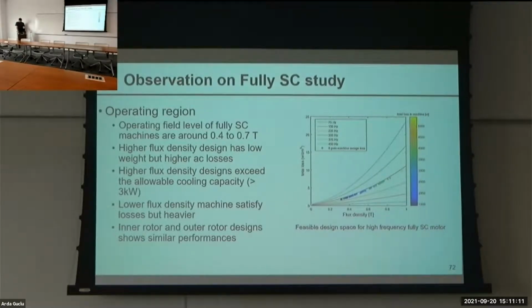So this is a study on an 8-pole fully superconducting machine. This is a study of flux density versus total loss, and you can see that beyond around 0.7 Tesla flux density, the loss exceeds the allowable cooling budget that we have for the plane. And the cooling budget is determined by the amount of liquid hydrogen that's stored on board the plane.